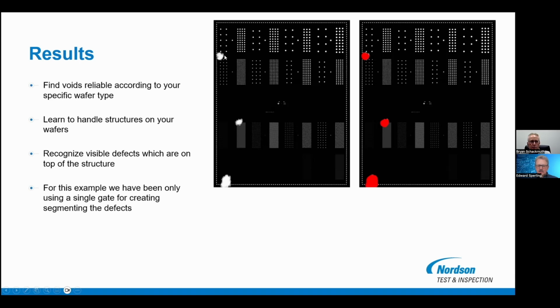So we see a bright white pixel. If you use a threshold, you're going to classify this bright white pixel and this defect pixel as a defect because it's the same intensity. It's the AIML that comes in and we can teach it what the defects are and tell it to ignore what are features. And that's really where we can use that AIML to get a better analysis on the package.